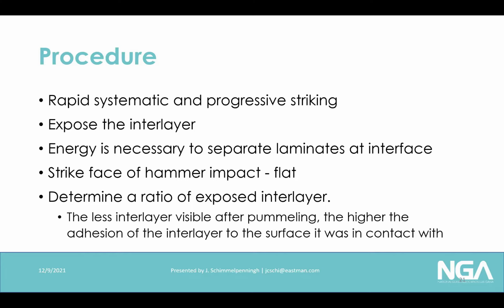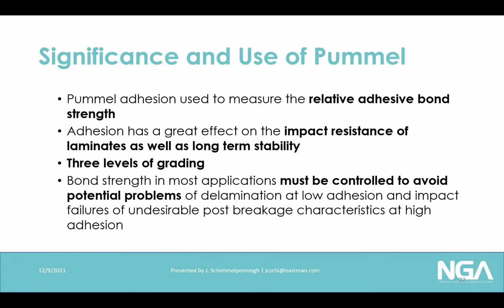Otherwise, you can skew the results. And so what it's doing is determining the ratio of exposed interlayer. The higher the amount of exposed interlayer, the lower the adhesion. So what you're really trying to look for, depending on your application, is that balance of exposed interlayer and glass to give you the performance attributes you're looking for. Again, it's a relative adhesive bond. It is not an absolute.